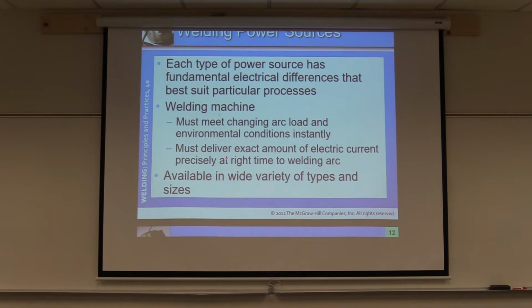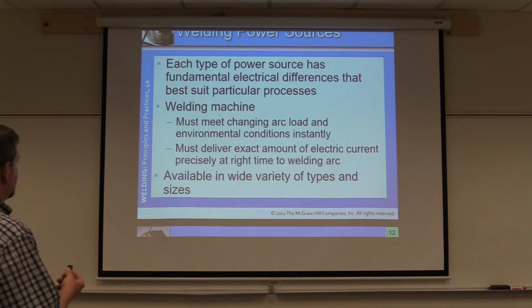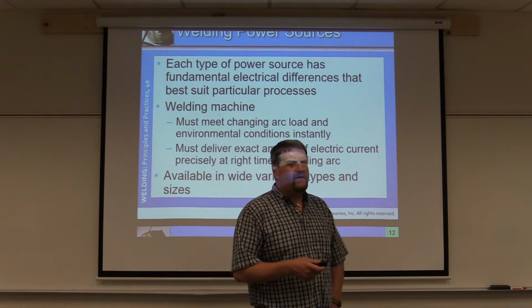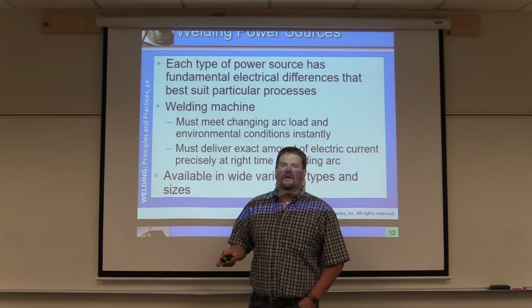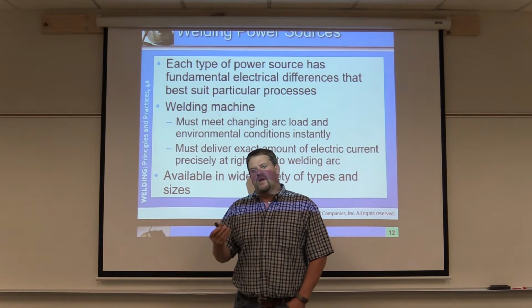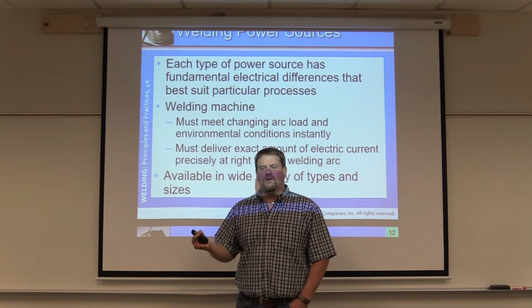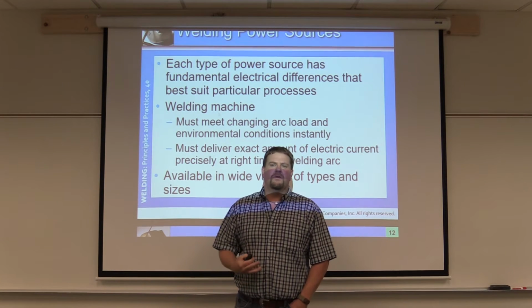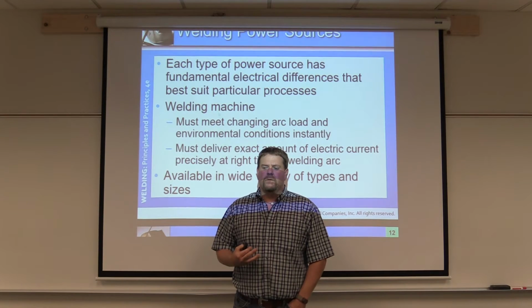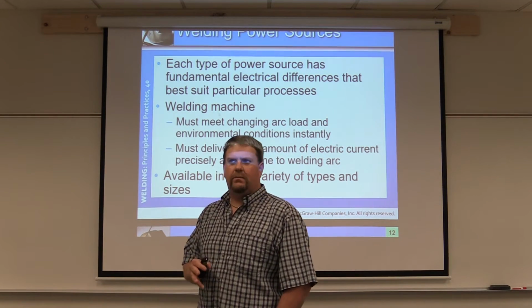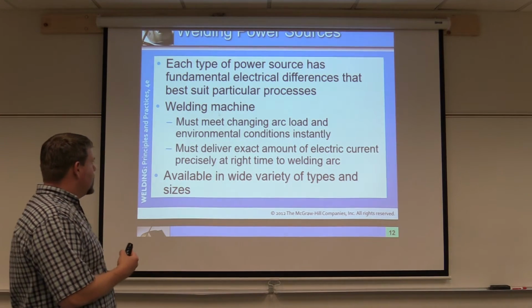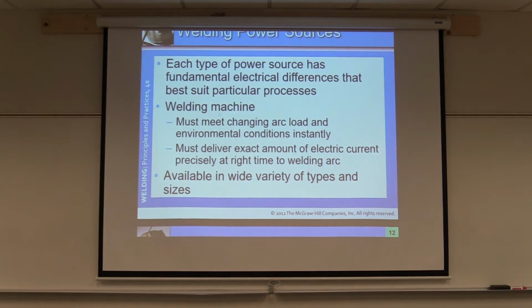This is a big piece right here. It must meet the changing arc load and environmental conditions instantly, okay? So say you have a machine that will only weld up to 85 amps and you're running 7018 electrodes, 1/8 inch diameter. You're going to need to maintain at least 105 to 135. You don't have enough machine to be able to correctly weld. I'm not saying it can't be done. The weld will be able to be started, but it'll be a very poor weld, not a pure weld, with a lot of issues within it. So make sure you have the correct machine, or the correct electrode.